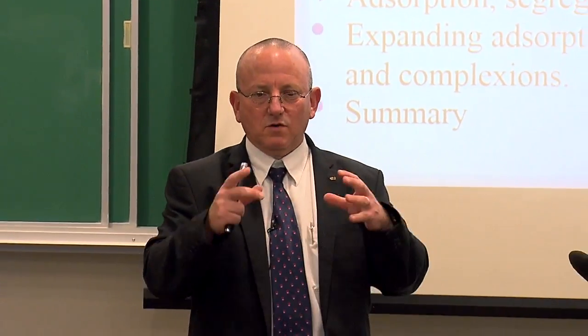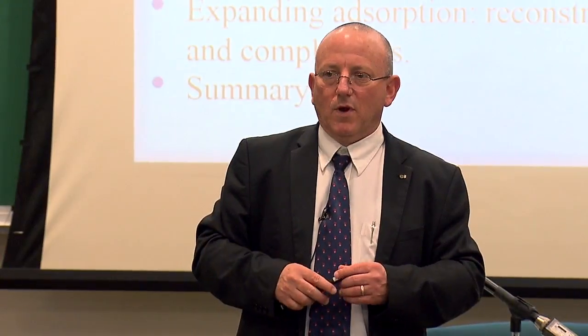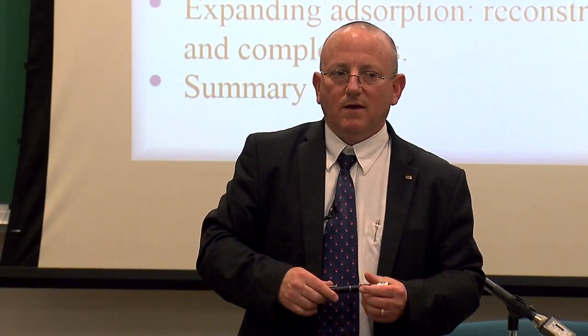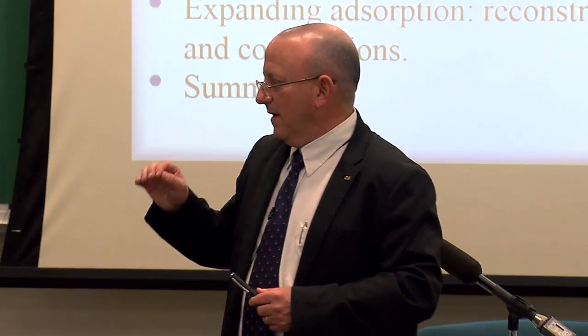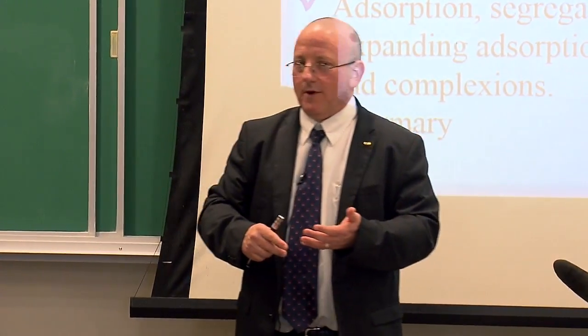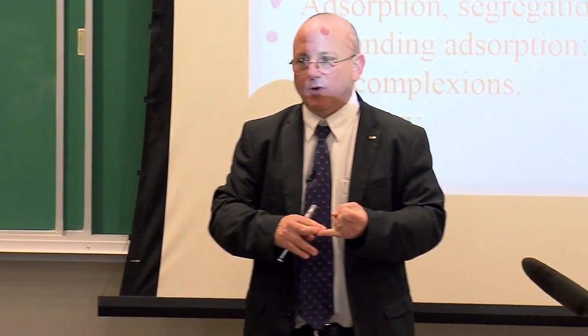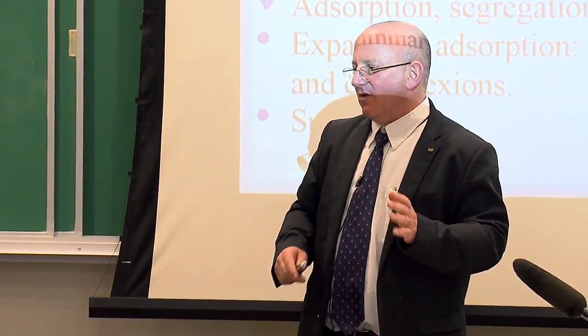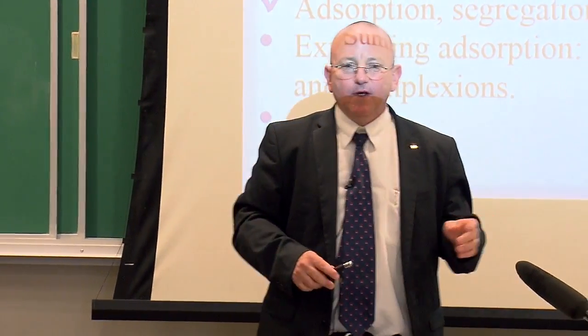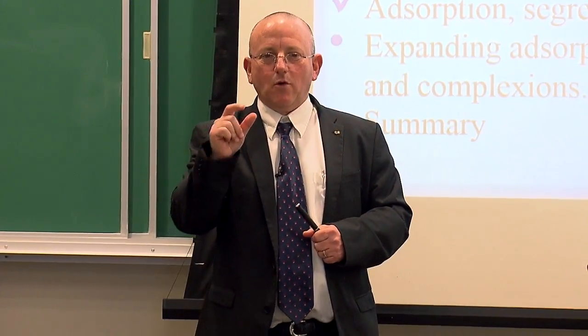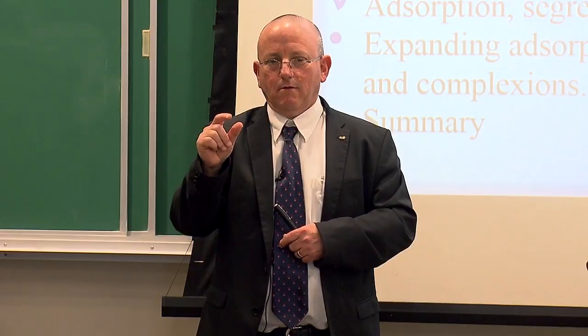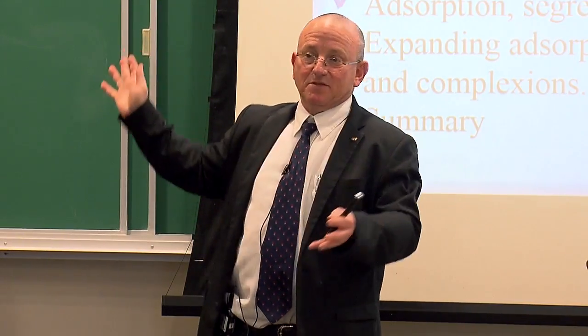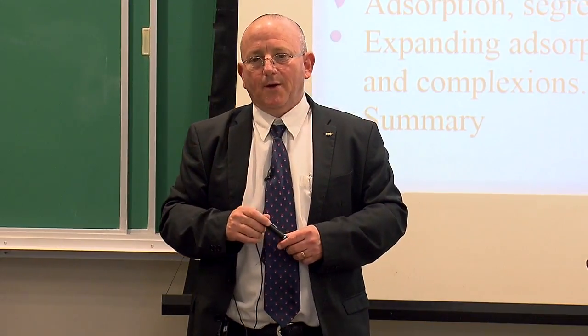The only difference there is that as I add more of the yellow stuff and it's partial wetting, those particles may be more numerous or they may get larger. But when it's a wetting film, that thickness will vary. So that's an automatic sign. Now I have to be careful with a word because they've been called so many things. They were called intergranular films or equilibrium films, although they're rarely done actually at equilibrium. Sometimes they were equilibrium amorphous films, and David Clarke actually called them at one point equilibrium wetting films. And of course, they weren't, because as you add more of the yellow, it didn't get thicker. You'd get precipitation somewhere, and those precipitates may grow, but the yellow didn't. So they were not wetting.